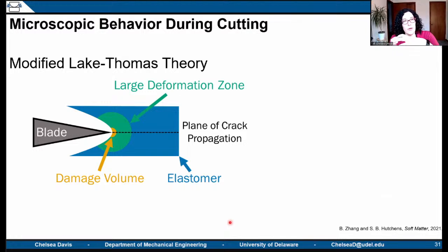However, in an elastomer, you have to think about not just the molecules right at the plane, or that dotted line where the crack is going to propagate, but there are also a lot of other polymer chains in that network that have to be moved out of the way and stretched and significantly deformed in order for that crack to be able to move forward. So you end up finding a much larger fracture toughness, or a much larger amount of material participating in the fracture event than was originally proposed.